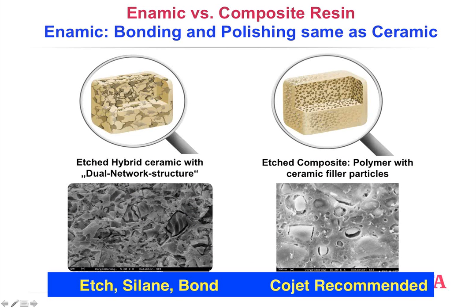With Enamic, you have this interconnected high-density network of ceramic. Etch it, silane, bond like you would any type of ceramic material, with a highly filled composite resin. With the small particles, it's a combination of glass, silica, zircon, which is a zirconium silicate, kind of like a glassy combination with zirconium, and zirconia. So some of the particles you can't etch at all. Some of the particles, like the glass particles, will etch away completely and dissolve completely in your acid. So you're trying to bond to a very highly cured polymer. And that's one of the reasons why CoJet is recommended, if you look at the website, to try and embed silica particles in the polymer so that you can bond to them with silane.